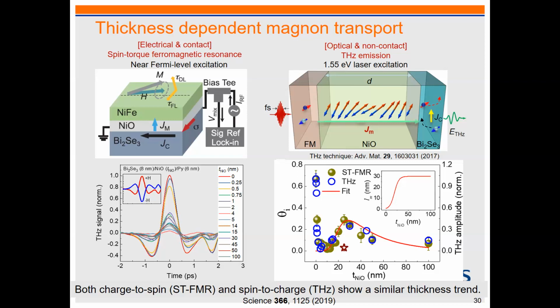The inverse process is that we can excite this magnet with a femtosecond laser. Then what happens? We can quench this magnetic moment temporarily. So then it can generate spin current due to the velocity propagation difference of spin up and down. And spin current will go through this nickel oxide in the form of magnon current. Then it can be converted to charge current in this bismuth selenide layer, and it will generate terahertz emission due to the oscillation of charge. So this is the spin to charge conversion. That's why we call this the inverse process. So we measure this as a function of nickel oxide thickness. That is shown in the open circles here. You can see it really follows the trend of ST-FMR. So indeed, this thickness dependence is correct, and we can see the existence of this conversion through the magnon current.